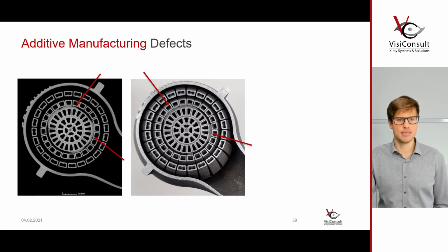Another big thing in additive manufacturing is residual powder. What you see on the left is residual powder left in additively manufactured parts. It's a heat exchanger here that is a great design. It's amazing what you can do with additive manufacturing. It's impossible to manufacture such a part with traditional techniques, but you see on the inside, in the CT scan on the left, there is some residual powder. Here, the whole internal passages are clogged. Here you see powder. And if you cut the part, you see it at the same areas. It's all filled with powder. And this can be critical because a heat exchanger only works if heat is actually going through the part.